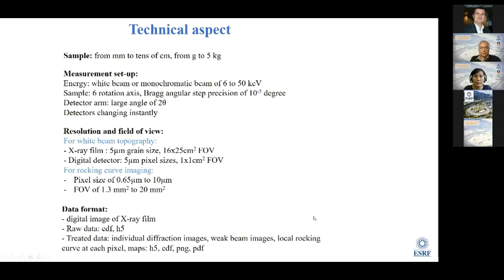And then at BM5, now I can give you some idea how it works. The sample can be a very small sample like a small diamond or a very big sample of 5 kilograms. We can have a wafer or we can have a very big ingot, no problem for us. And for the measurement setup at BM5, we can have white beam to do white beam topography or monochromatic beam.